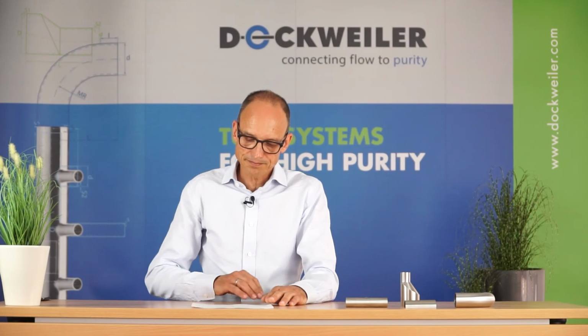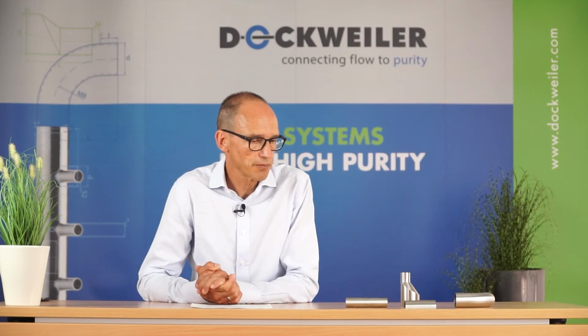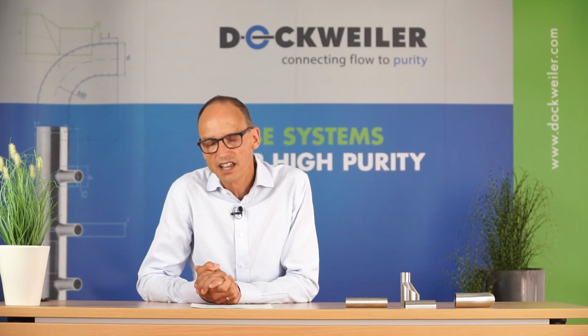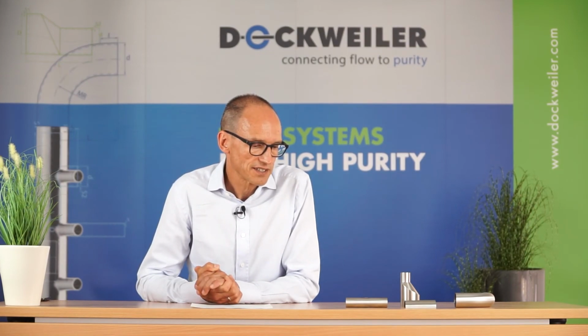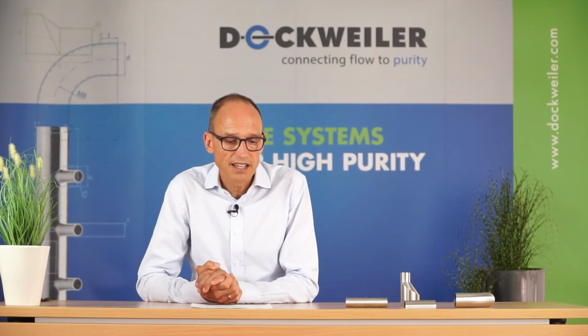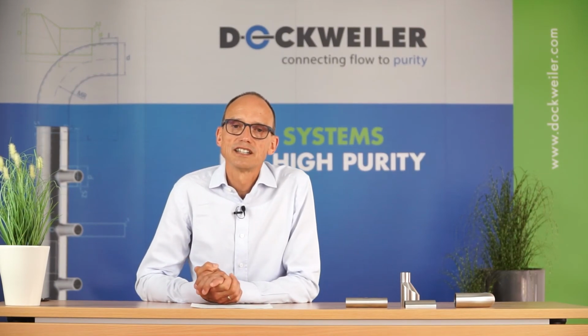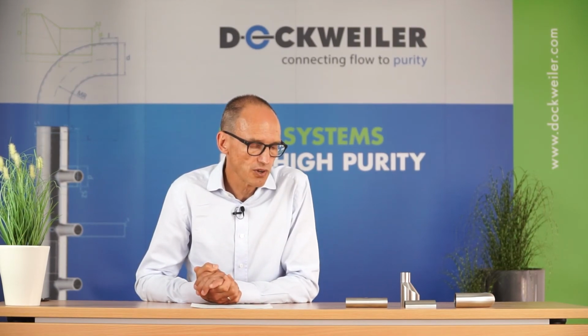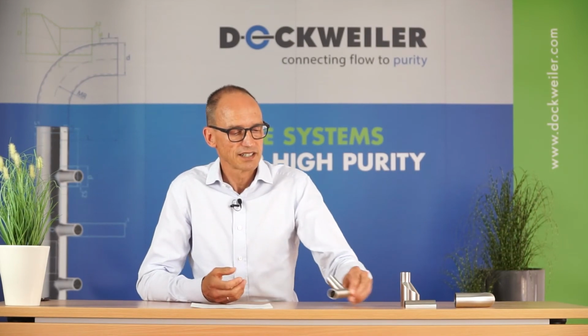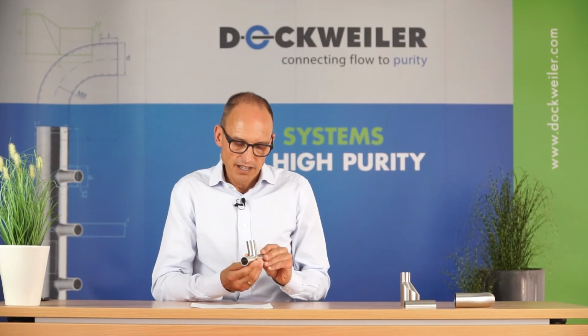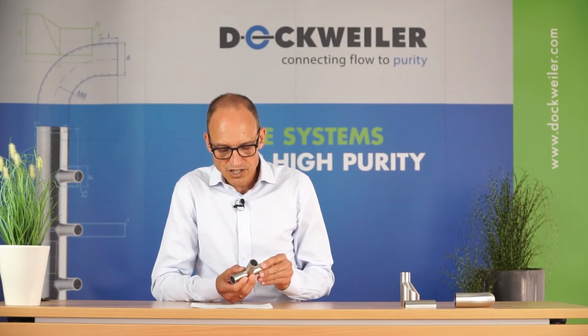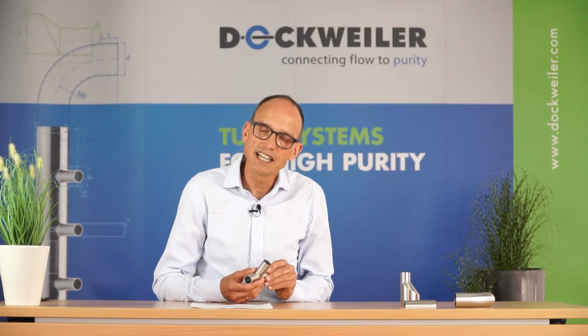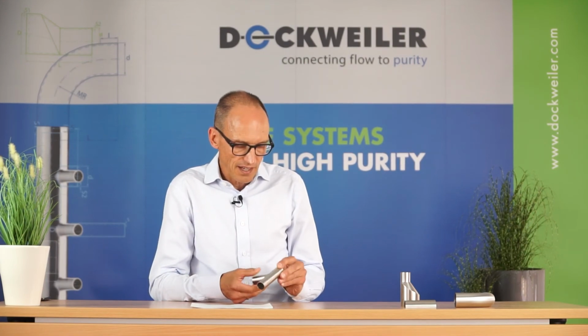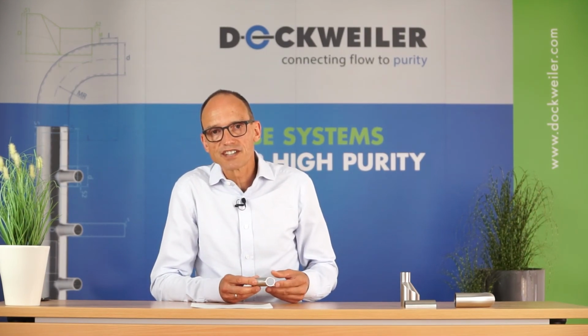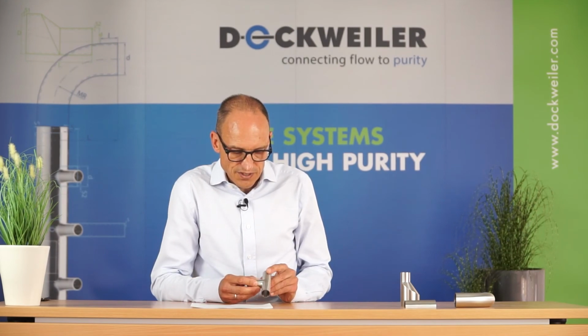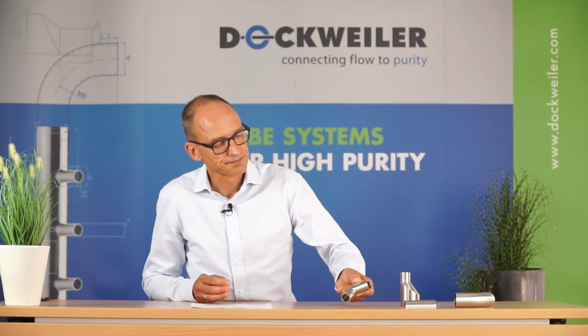And the second new topic here is that there are two options for the T-piece weld. Again, this is absolutely the same as with ASME BPE. There are two options. The first one is that the T-piece weld is to be polished, flush and smooth with the base metal on the ID and the OD, still maintaining the minimum of 75% of the nominal wall in all areas.